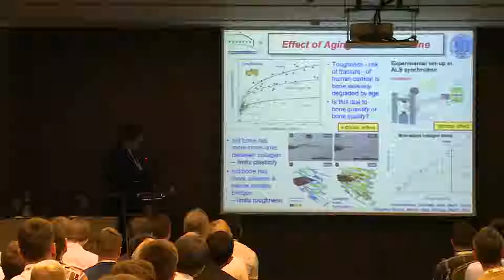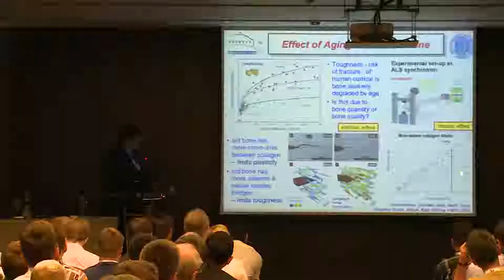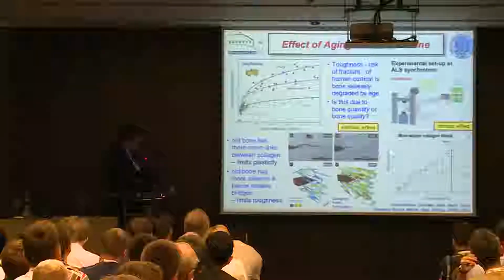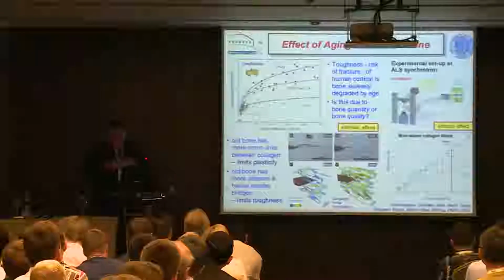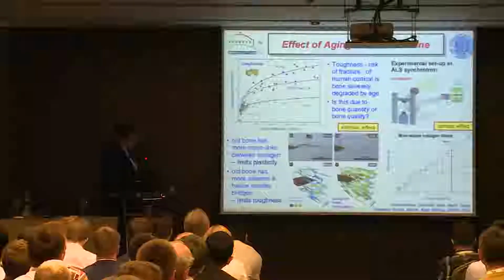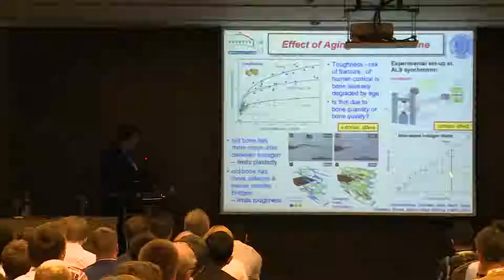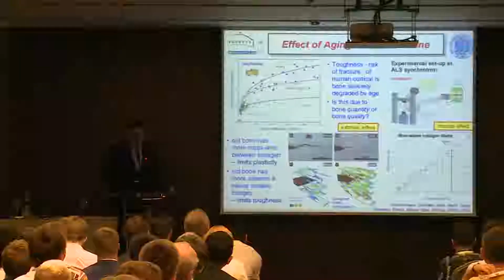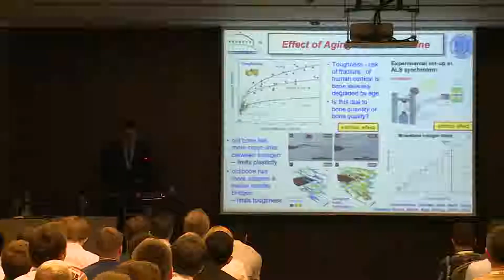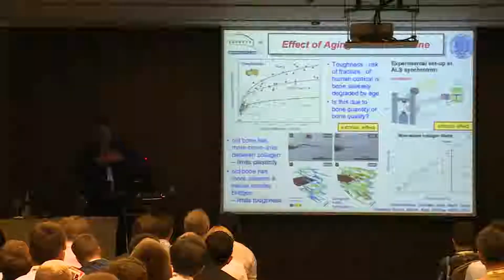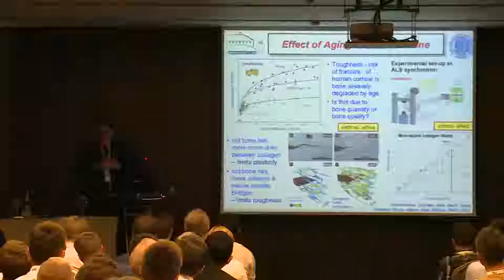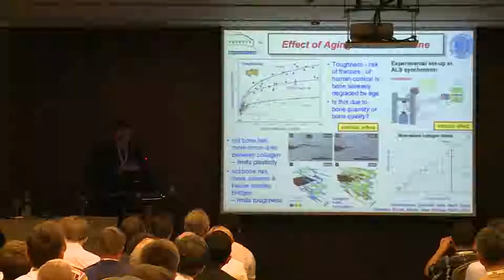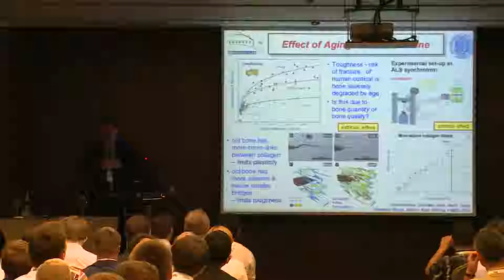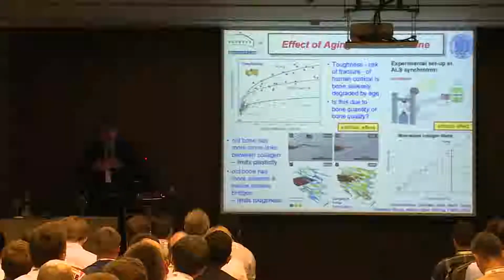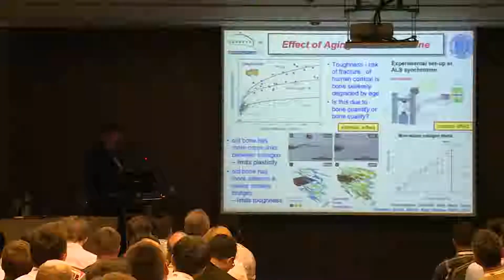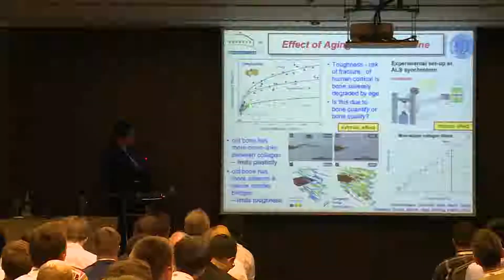And what you find is, this is the strain in the collagen, this is the strain in the bone itself. For young bone, let's say about a 1% strain, you can see virtually all the strain is carried by the collagen, of course, because that's the flexible part of bone. But if you look at old bone, it's a very different story. Now, for a 1% strain in the bone, half that strain is carried by the collagen. So the collagen is less effective. And what basically happens is, instead of sliding apart like this, it locks up. And it locks up because of cross-linking. Your collagen has many types of cross-links in bone. These are called non-enzymatic cross-links, and they basically lock up the process. And it's just like an embrittlement in a metal. You just lose ductility. So those are, again, these two different classes of mechanisms. They're very different. They operate at very different scales, but they all affect the toughness.